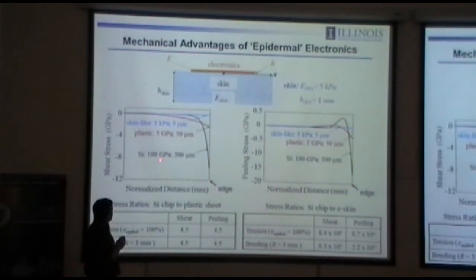And you can do that for 3 cases. One is the case of a silicon chip that you just glue to the surface of the skin. And this is the least attractive way to do skin-integrated electronics, but just as a point of comparison, 100 gigapascals, 300 microns. If you think about conventional flexible electronics, a lot of people working on that, this is electronics on a sheet of plastic, where the plastic might be polyimide in modulus of 5 gigapascals and a thickness of 50 microns. And then you can think about skin-like, more in the regime of this temporary tattoo, 5 kilopascals and 5 microns. And then you look at the peak stresses, and you can compare them.